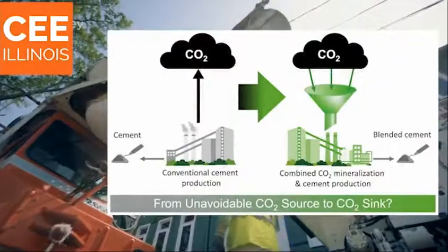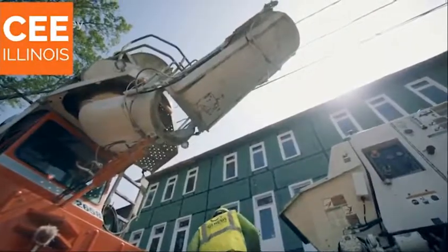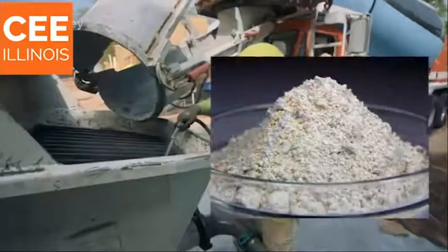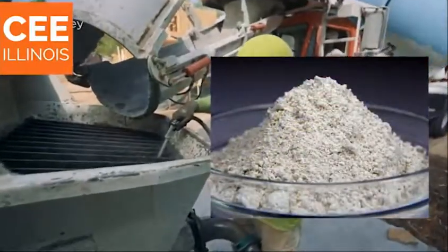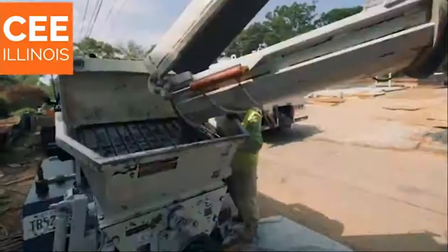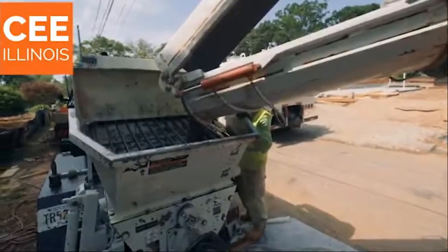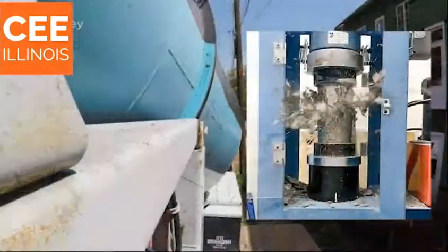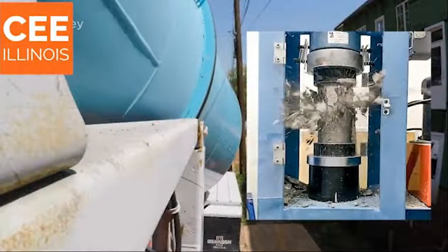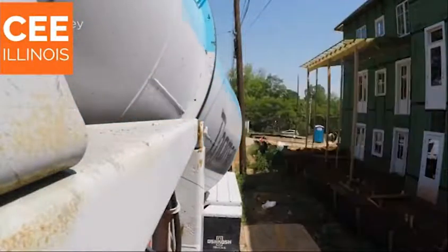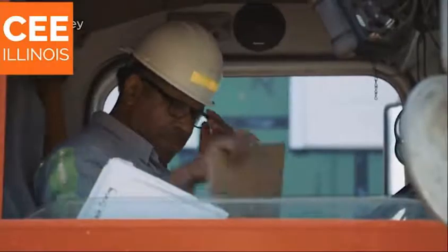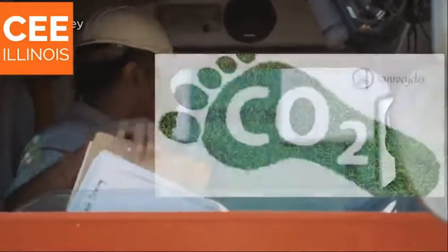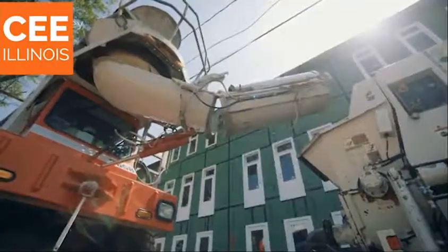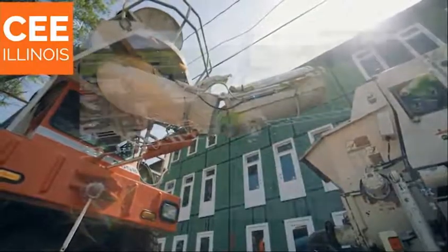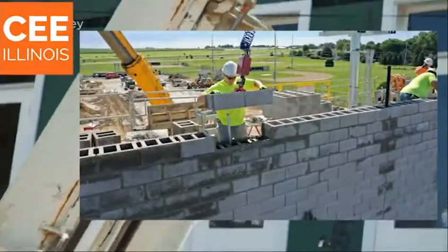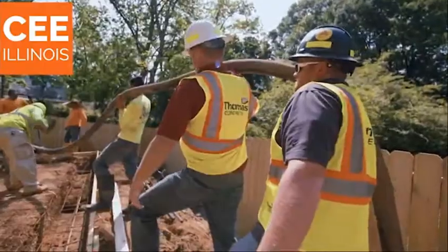During the carbonation process, the gas reacts with the steel slag to form stable calcium carbonates. CO2 is permanently captured and converted into these products, filling the voids of the matrix to form a dense structure and giving concrete its strength. By eliminating cement, which forms around 12% of traditional concrete, the technology reduces the carbon footprint of the material by half. This technique has been mainly used in concrete masonry units manufacturing, where it has demonstrated highly favorable results.